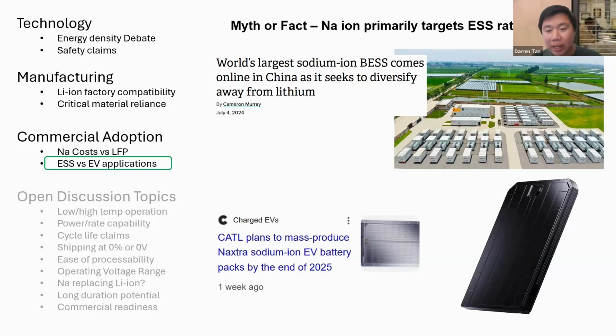Edmund asks, is NFP electrode very heavy? I'm assuming you're talking about NFPP, the pyrophosphate version. So it's not heavy, it just has a low capacity and low volumetric energy density. So the reversible capacity of NFPP is about 90 milliamp hours per gram, which is significantly less than a lot of layer oxides. It also has a terrible tap density. So its tap density is something like 0.6 or something like that. And after compaction is just under 2 grams per cc. So it takes up a lot of space. So for the same can, you actually get much less amp hours compared to many other chemistries. It's improving, and I'm interested to see where it goes in the next few years.